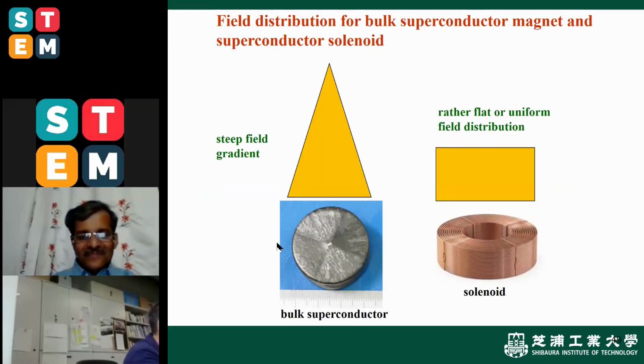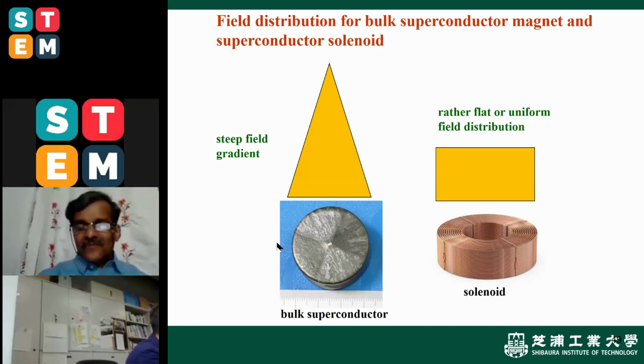So this already shows the magnetic field distribution has a steep field gradient, very sharp. This is the bulk superconductor. When you see the solenoid coils, it is rather flat and uniform. So the strong and steep field gradient generated by HTS materials will control the drug and the distribution of the particles in this material.